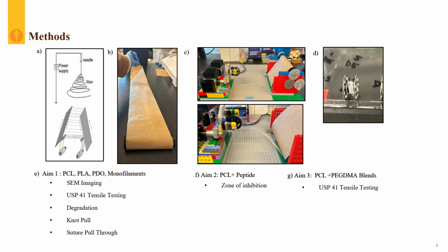This system is pretty unique given that most nanoyarn fabrication systems do not allow for post-rolling capabilities, have limited control over alignment, and have limited length capabilities. After we create our nanofiber sheet, we put this onto a custom yarn spinner where we control uptake and twist to have a resultant twist per inch of 5. And then we are left with a bobbin of nanoyarn.